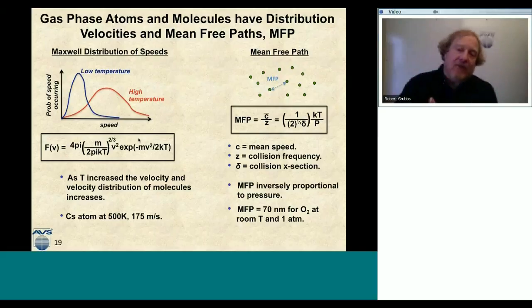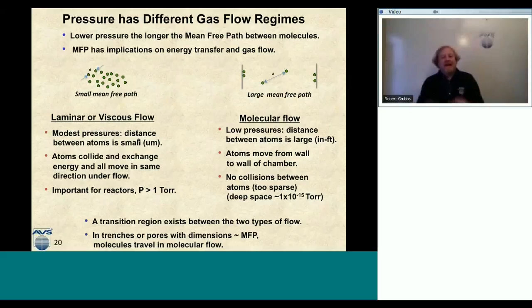So I said that mean free path was a little more important, and that is shown on this slide here. So the mean free path or pressure has different flow regimes. On one side, we have this laminar or viscous flow that we are all familiar with in ALD reactors, but we also have something called molecular flow. And these two flow conditions are really dependent on the mean free path of the molecules in the gas phase. So the lower the pressure, the longer the mean free path. The higher the pressure, the shorter the mean free path.